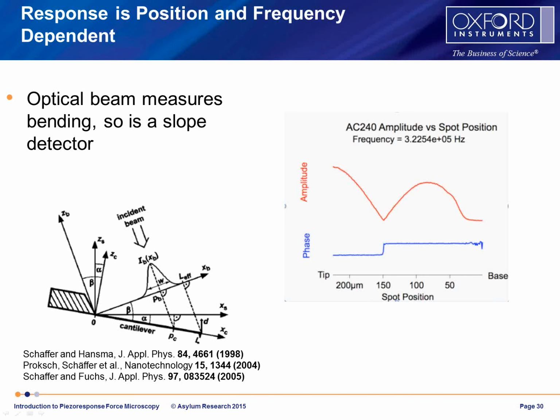So the most striking result from the previous slide is that the response that we measure is not only frequency dependent, but it's position dependent. And by position, I mean the position of the optical spot, this incident beam on the cantilever. So where that shines on there, that position along the length determines the sensitivity. And that's really brought out here. This is just a slice from that movie I played earlier. If we put our optical beam spot right here, we maybe measure, call it 100 millivolts. If I move that beam just a few microns, 10 microns, 20 microns towards the base, I'm going to measure 50% of that amplitude. And so my D33 here versus here will be 50% smaller.